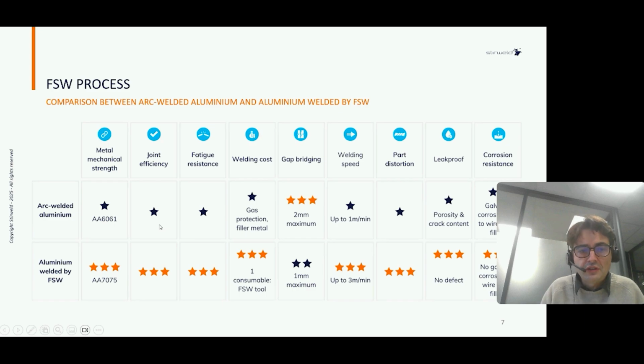Second point is the joint efficiency. As you know, it can be 6000, 2000, 7000, which are heat treatable aluminum alloys. So when we weld, we increase the temperature, so we reduce the mechanical strength because we reduce the temper of the materials. As friction stir welding is done at lower temperature than arc welding, in fact we reduce the strength less. So if we compare the joint efficiency, the joint efficiency after friction stir welding is generally 2 times higher than after arc welding.